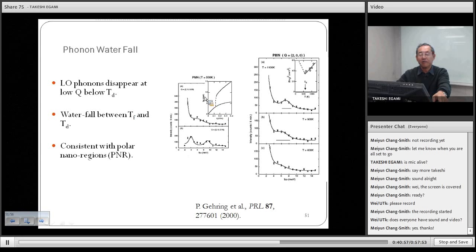And this is because phonons become localized. Okay? If phonons are propagating, then they show up in a regular S(Q, omega) measurement, because the wave vector is well defined. Okay? But if phonons are localized, there's no specific Q. There's no wave vector. Okay? You know that you can make a wave packet by summing up all these wave numbers, right? So a localized phonon represents a wide distribution of wave number k. So you just cannot see it by this regular S(Q, omega) measurement, and yet the formation of such a local state is considered to be important in understanding this relaxor ferroelectric behavior.